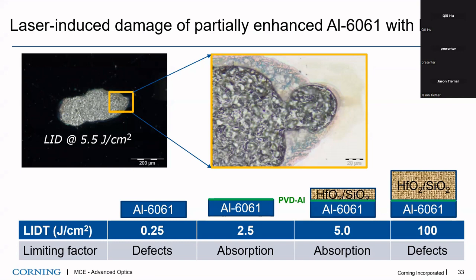And then, as soon as the light intensity increases, these seeds absorb the laser energy. In the meantime, because of this shape, the boundary of the cone is relatively weak, so there is a nodule ejection effect as you irradiate. That's also an additional damage mechanism. The nodule is ejected and then the laser hits the substrate without the nodule. So a couple of mechanisms happen, maybe simultaneously.